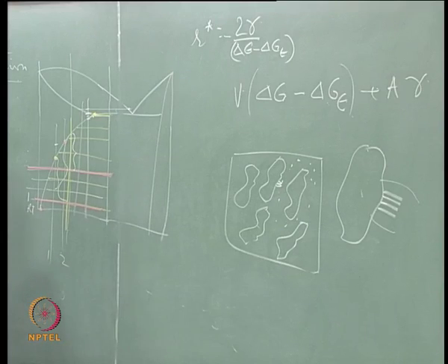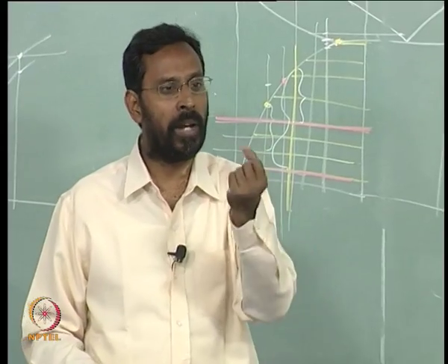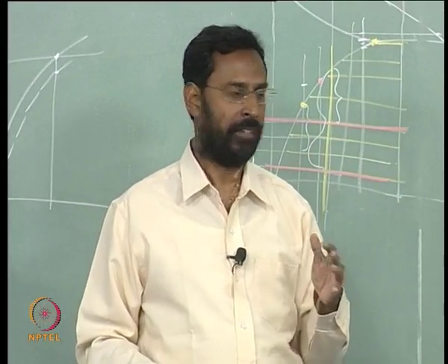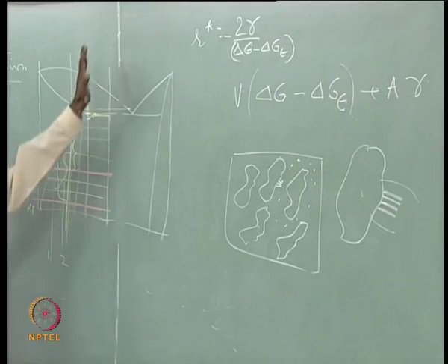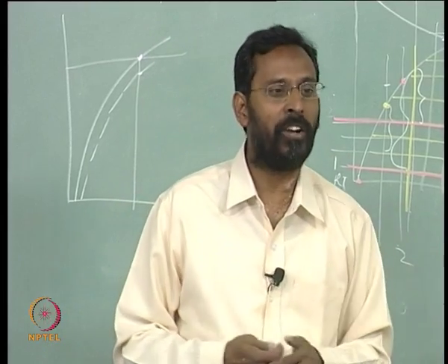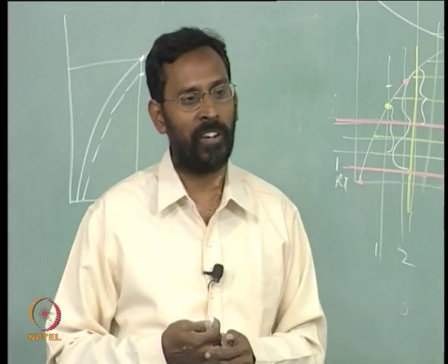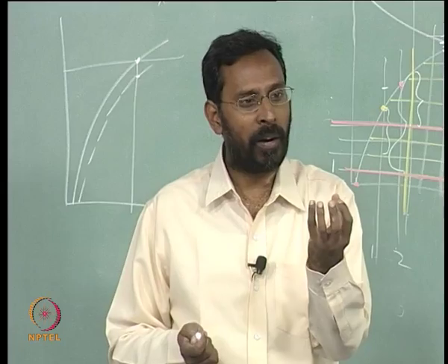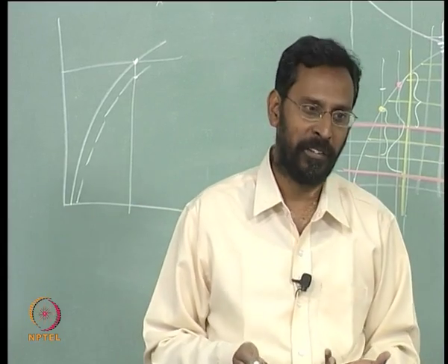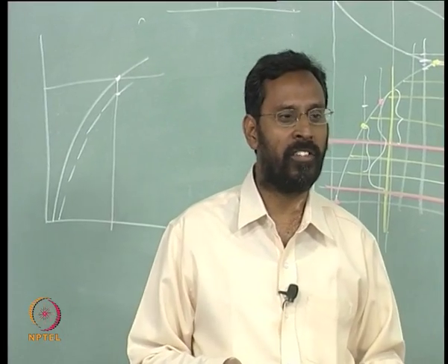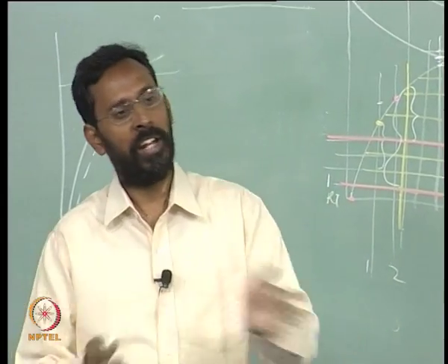Similarly, during liquid to solid transformation also, sometimes you may get them, particularly when you are cooling rapidly. For example, assume that this alloy is being cooled very rapidly. The theta phase, which is orthorhombic, is difficult to nucleate. So, the system will try to choose the phase which can easily nucleate, a metastable phase, but that would always remain metastable; if you heat it, it will come back to the theta phase.